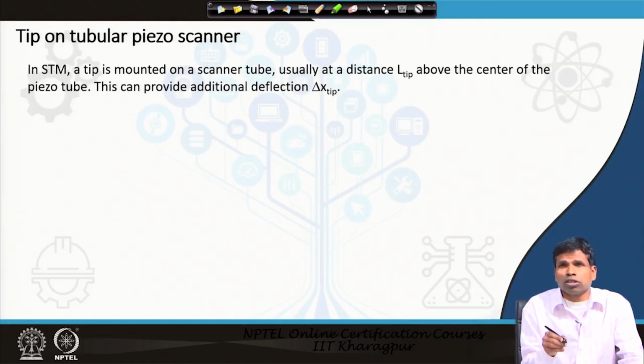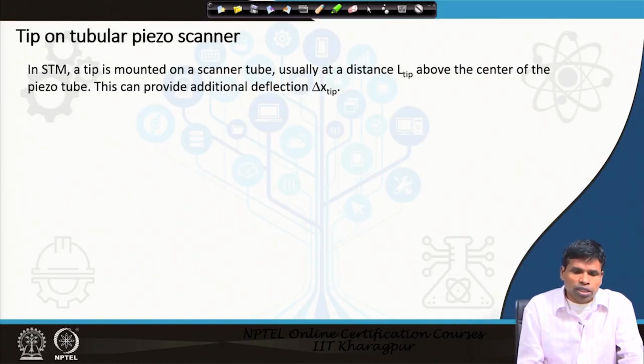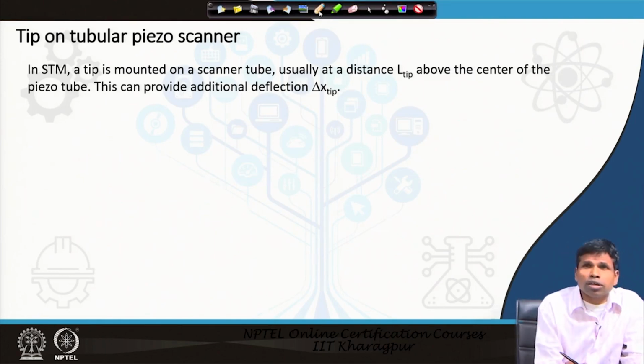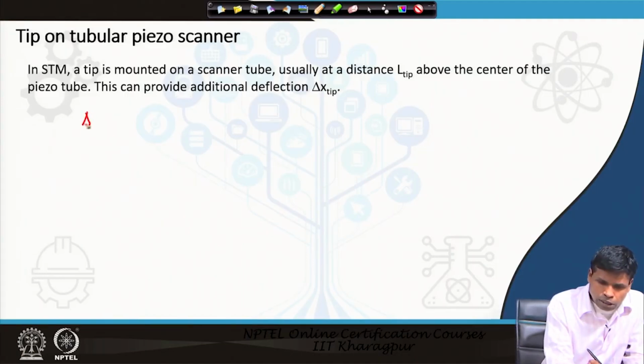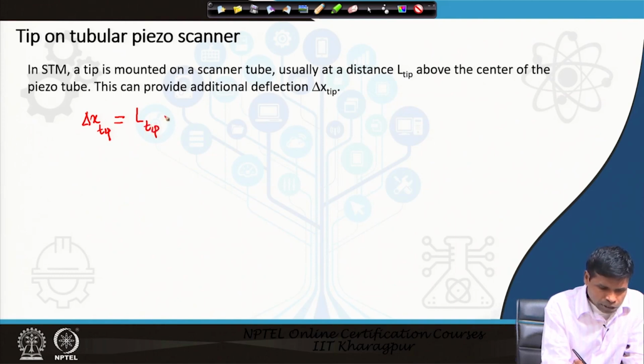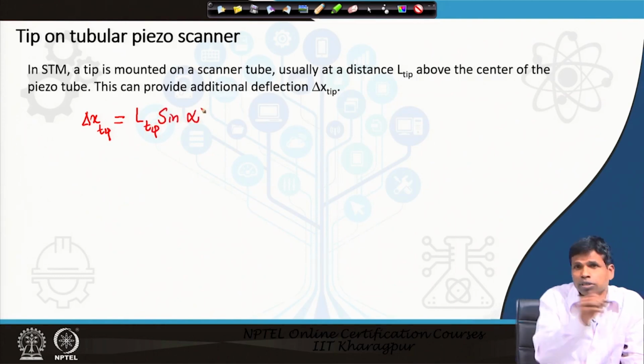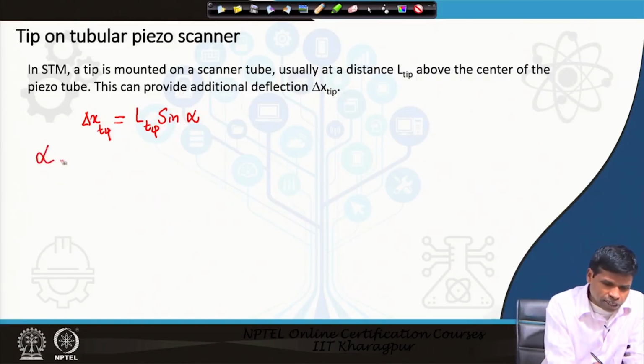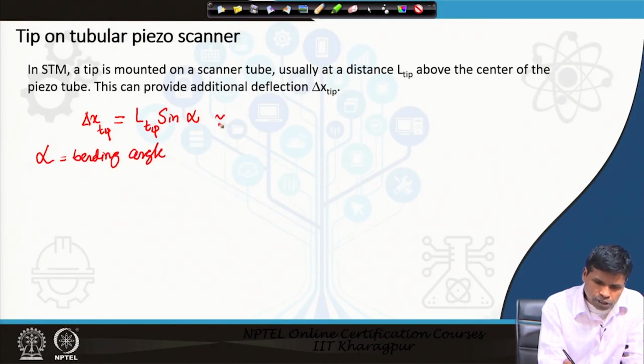So, a tungsten or platinum iridium tip is fixed on this tubular piezo scanner to measure the current. Normally this tip is placed at a distance L tip above the center of the piezo tube. Thus it can provide an additional deflection del x tip. As it provides additional deflection, we can find that del x tip is equal to L tip sin alpha. We can write sin alpha because it is in bending motion. Alpha is the bending angle, and it is quite small.